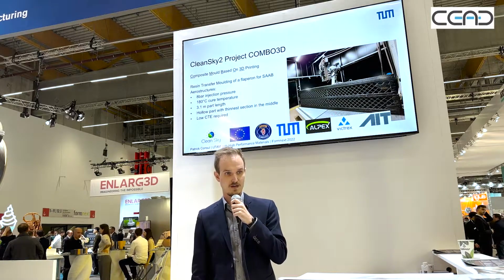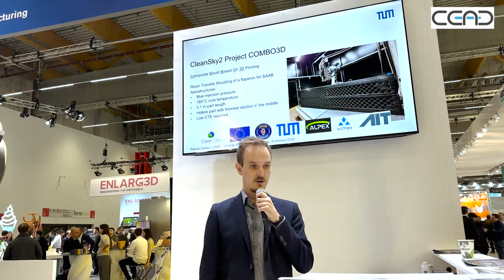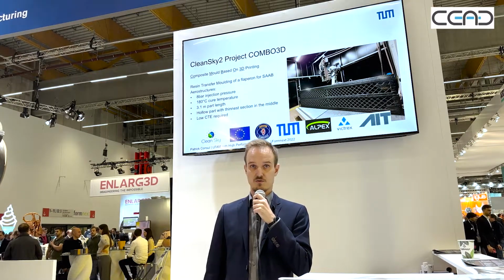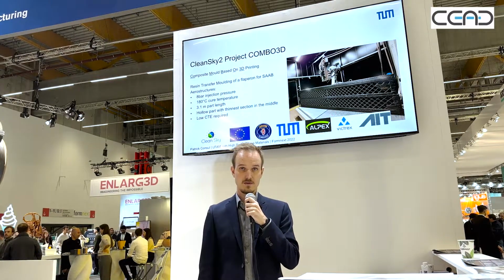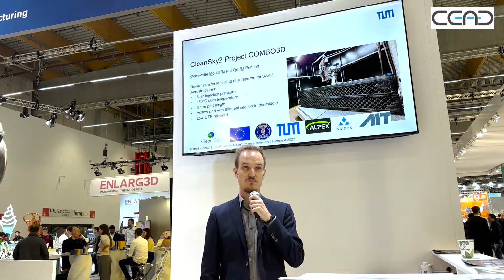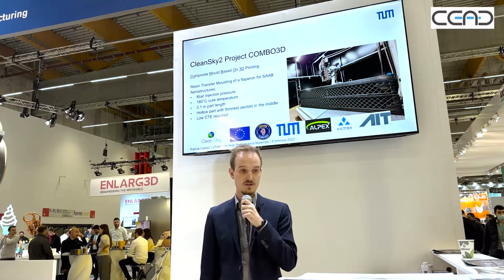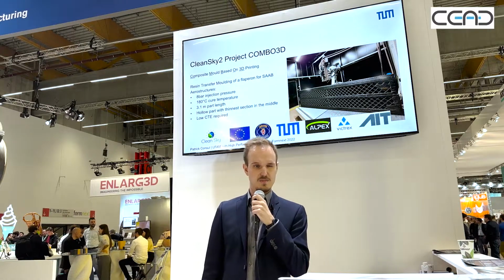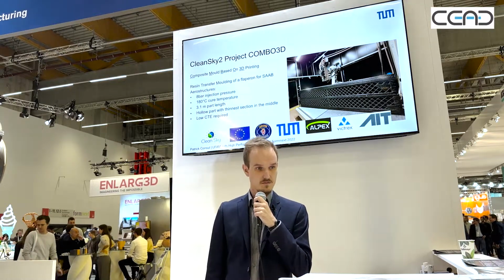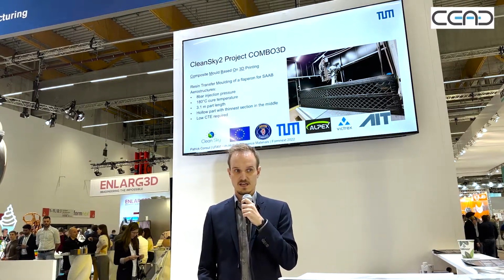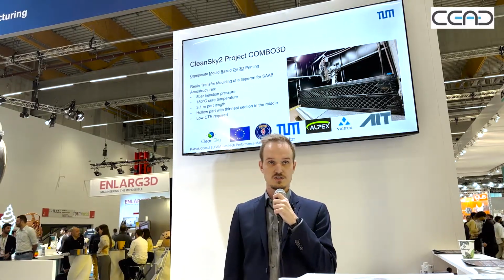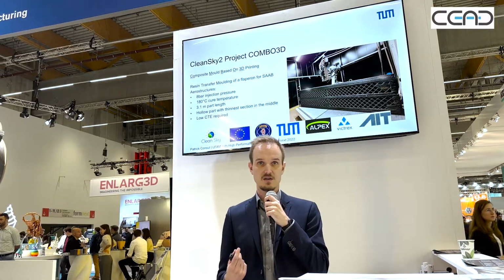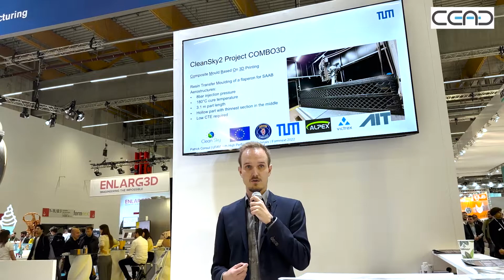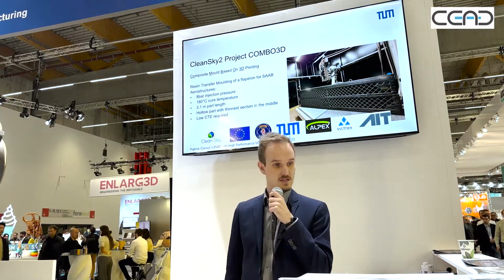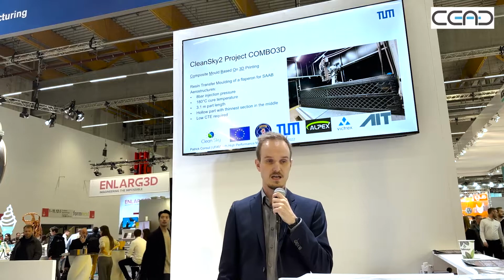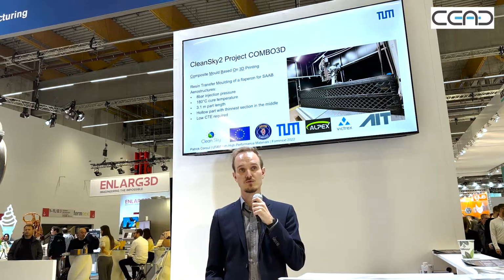So I want to talk about a Clean Sky 2 project in which we printed a resin transfer mold for Saab to produce a flap run for an Airbus A350. The part you see in the picture is about 3.10 meters in length, and it has to withstand quite tough process conditions. You inject resin into it at 8 bars pressure. You then cure the whole thing at 180 degrees Celsius. It's quite long, and the part you produce with it is actually hollow.